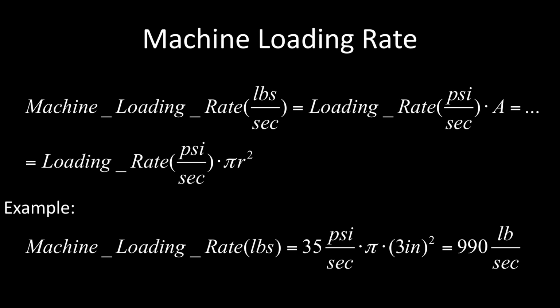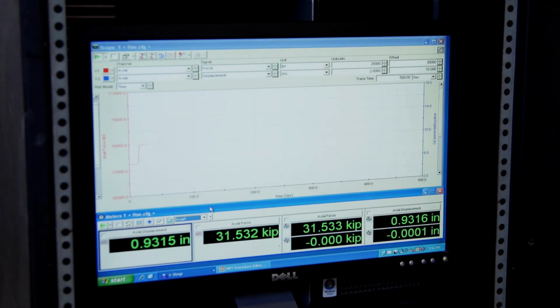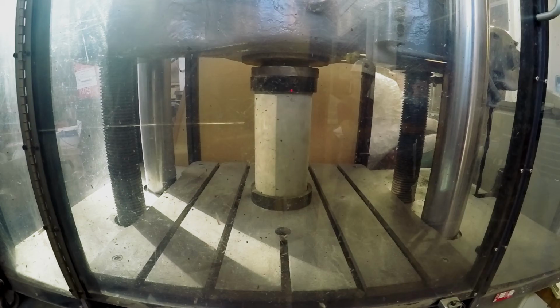Due to the larger cross-sectional area of the 6-inch by 12-inch cylinders, a higher loading rate is required to achieve the same target of 35 psi per second. The TA will input the calculated loading rate into the testing software and then begin the test.